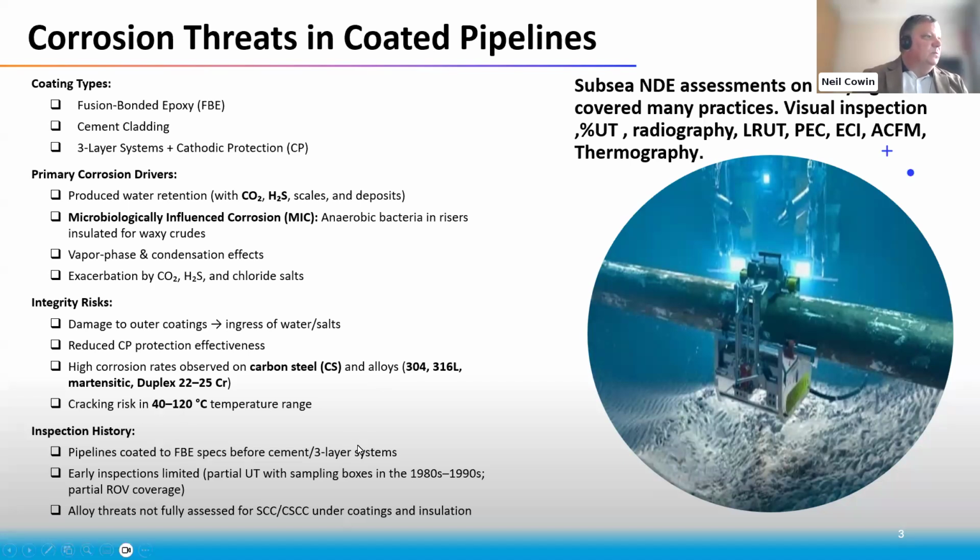So we have had instances where that became an issue with us in the 90s, in particular with development of alloy pipelines that I remember for Norway. So we had a lot of 13 chrome, 15 chrome, 16 chrome that we analysed at one time for pipelines, and we had major cracking issues after 3 or 4 years of development there as we moved into the higher grades back into the 90s, because very few super duplexes and duplexes were used in topsides design or process design, but we did use them extensively for downhole